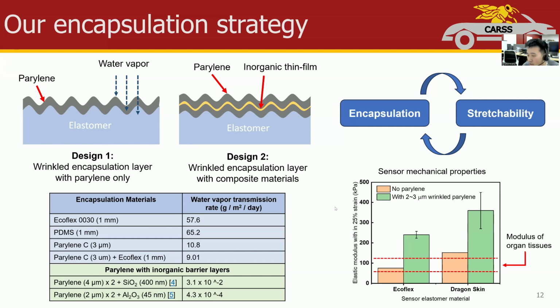The figure on the right side shows the modulus of our sensors after forming 2 to 3 micron thick wrinkled Parylene, which is still higher than the modulus of most organ tissues. One way to solve it is to add a thin inorganic layer between two Parylene layers. The inorganic layer has much better encapsulation performance, and we can reduce the Parylene thickness to reduce the overall stiffness. For this part, we're still working on it.